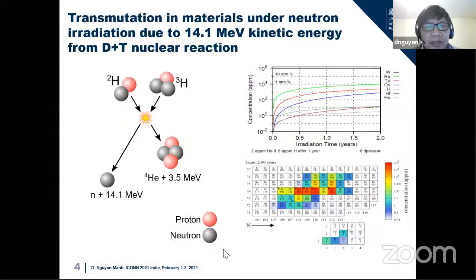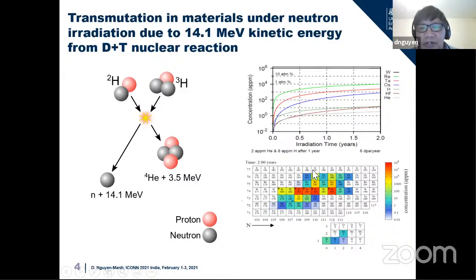Okay, so it is going to change the material properties. For example, if we use the first one as tungsten, then after 2 years there is some amount of rhenium, osmium, and tantalum being produced, as I showed in the first slide. It is evaluated as changing the composition as a function of time, and the time here is in years.